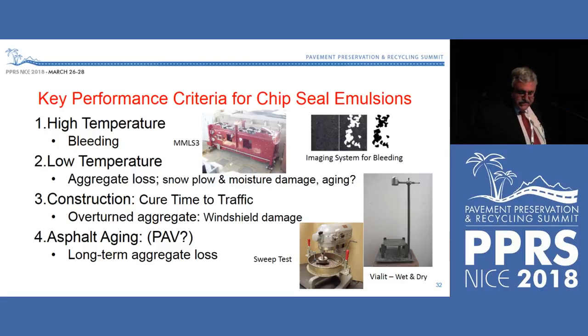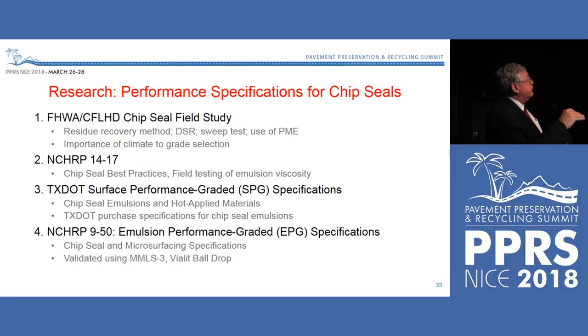And finally, the aging issue: again, we're really struggling with whether we need a PAV long-term aging test for residues or not. There are four research projects to refer to. One is headed by the National Center for Pavement Preservation, done for FHWA and Federal Lands, looking at different possibilities for test methods. There is a chip seal best practices study from NCHRP that developed field emulsion viscosity testing, because we feel it's more appropriate to test viscosity in the field as materials are applied. And then two specifications for chip seal residues have been turned into AASHTO already from two different research projects.